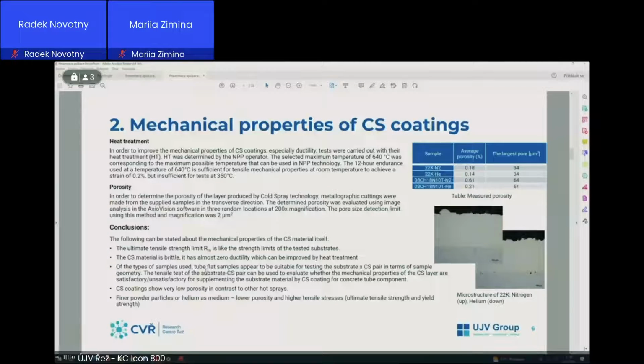The tensile test of the substrate cold spray pair can be used to evaluate whether the mechanical properties of the cold spray layer are satisfactory for supplementing the substrate material by cold spray coating for concrete tube component. Cold spray coatings show very low porosity in contrast to other hot sprays. It's good information from the point of view of inspectability. I will speak about it later. And finer powder particles or helium as a medium means a lower porosity and higher tensile stresses.